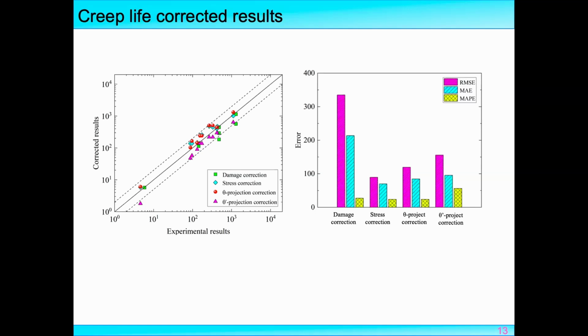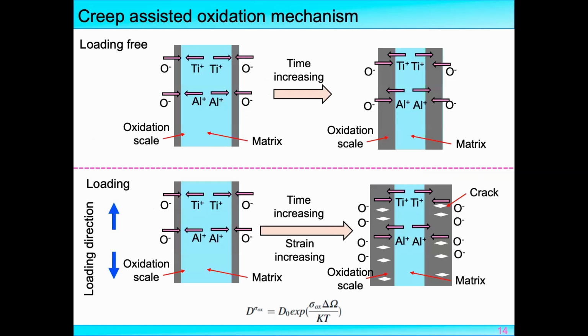However, we consider that this method is too complex, and this method is very simple. We recommend that when we correct the creep life for a miniature specimen, we can use the stress correction method. And finally, I want to discuss the creep loading assisted oxidation mechanism. So why?